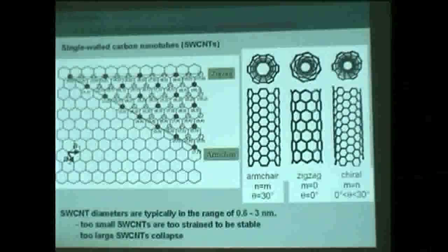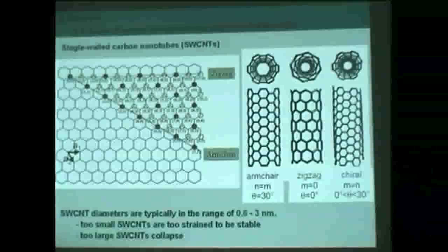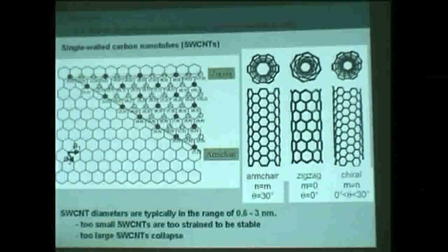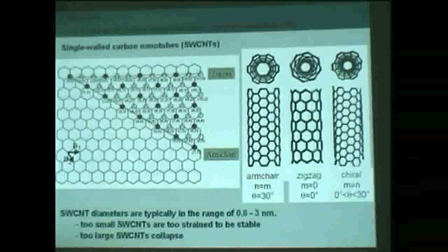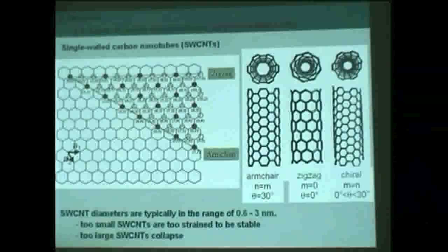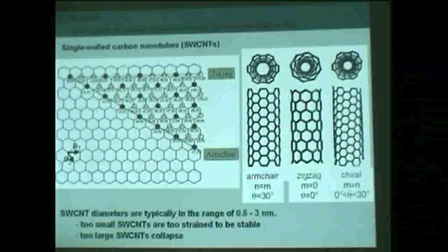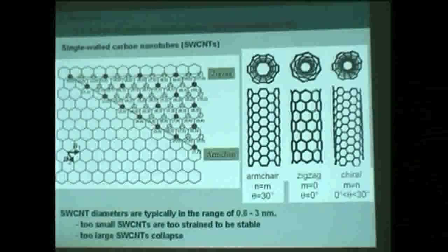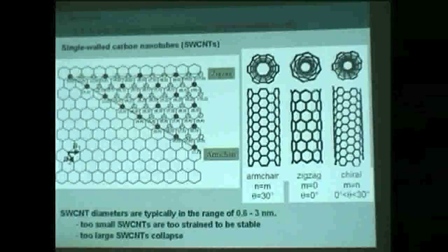Why those values? If you want to make a tube with a diameter less than 0.6, you get a lot of strain, because sp2 bonding does not like to be bent if there is no pentagon or heptagon - it should be flat. Do you see any pentagons or heptagons here? There is none. However, there is some curvature, a local curvature, not Gaussian. This curvature is low, but to get it without pentagons or heptagons, you need to put some stress on those sp2 bonds.